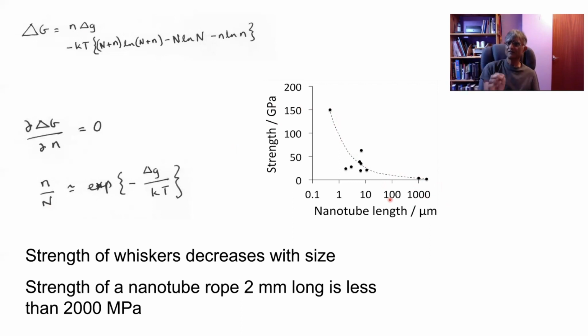And exactly the same principle applies to graphene. It's complete nonsense to talk about the strength of graphene being 200 times stronger than steel. It's only 200 times stronger, as are carbon nanotubes, when the size is incredibly small, okay? Because you are relying on the carbon-carbon bond, not on defects, and defects will be there as soon as you scale it out, okay? And of course, the strength of graphene and of carbon nanotubes is highly anisotropic.